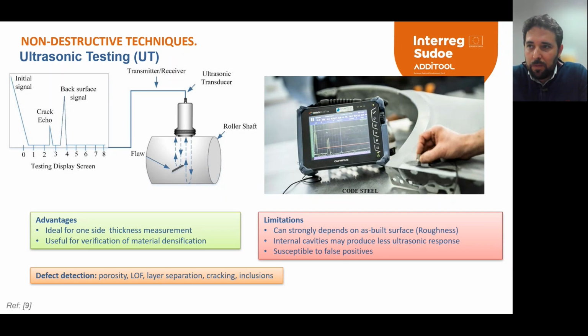With this technique, it is possible to detect porosity, lack of fusion, layer separation, cracking, and inclusions. As main advantage, it is a quick inspection. But on the other hand, one of the main limitations when inspecting AM components is that it strongly depends on the surface roughness. So you may consider the inspection where the surface is machined.